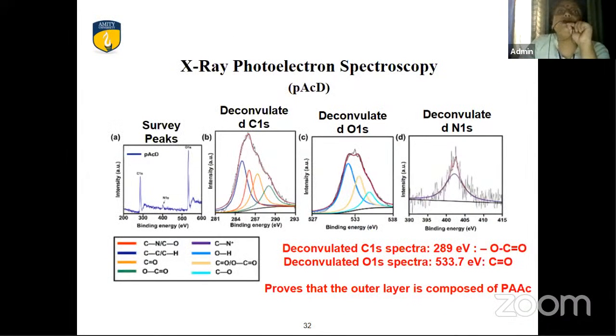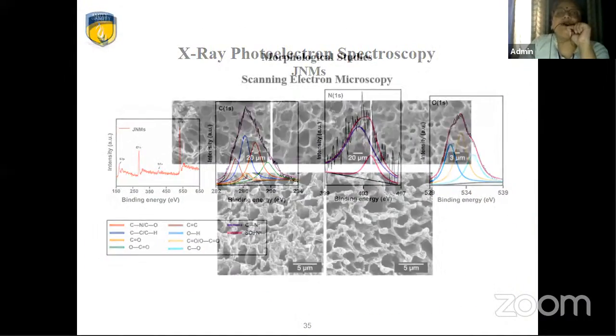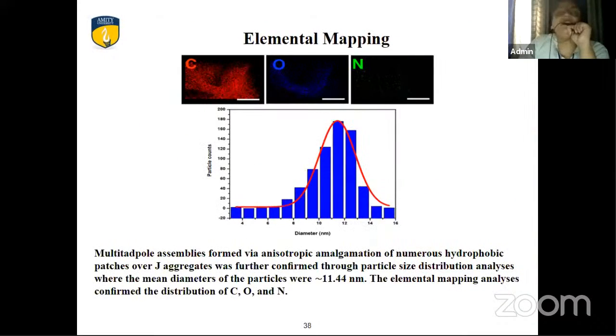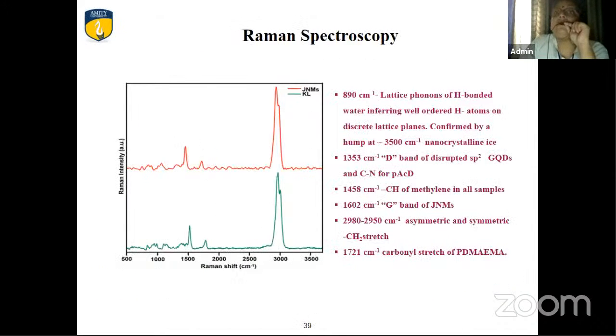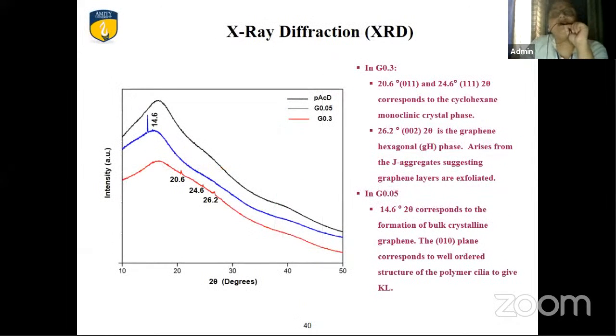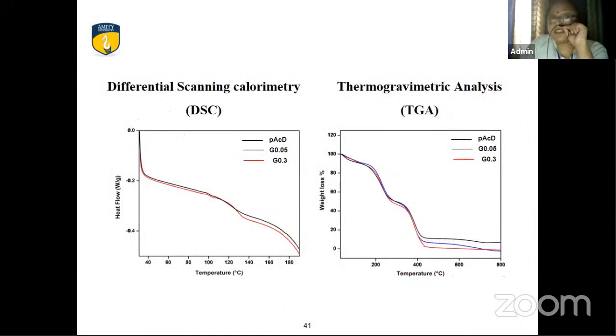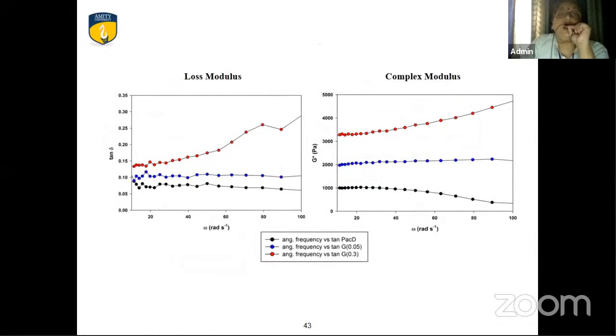This has been validated with X-ray photoelectron spectroscopy as well, which I'm not going into the details of, because if I go into the details, it is very difficult to finish. We have done all the studies: elemental, and Raman features are also very important to look at the lattice phonons to understand the mechanism, because until and unless we touch base with all the experimental data, we cannot come up with mechanistic insight into how these exotic nanostructures are formed. We went to the XRD diffraction pattern. We went in depth to understand, and we are the first to report this sharp peak at 14.6 degree 2 theta, which we say is for the polymer cilia giving rise to the Kagome lattice. We have done differential scanning calorimetry, thermogravimetric analysis, rheology, loss modulus, complex modulus.